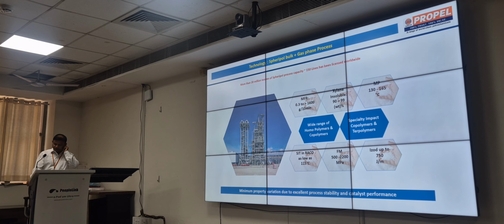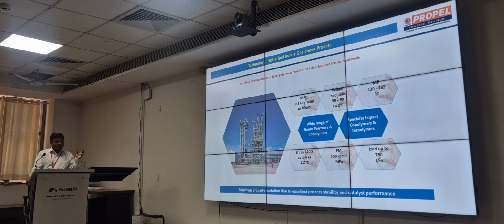So this is the broad range of different products, with MFI from 0.3 to 1600 grams per 10 minutes. 1600 MFI material is used in diaper applications. We produce non-woven products through the spunbond process, but for hygiene applications, a multi-beam process has to be used, spunbond as well as meltblown. For meltblown, the MFI of the products is 1600 to 2000. So just think about how the control can be done for such high flow material in the reactor system.